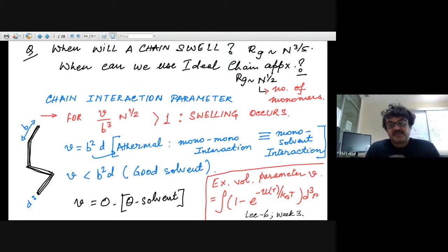That's different from the excluded volume, because the excluded volume will be the diameter, right, of the monomer. So the two monomers cannot overlap. But even if they can't overlap and there's some excluded volume, right, basically there could also be attraction between the monomers. And so this excluded volume parameter v takes into account both the solid diameter of the monomer as well as the interaction, if there is an attractive interaction.